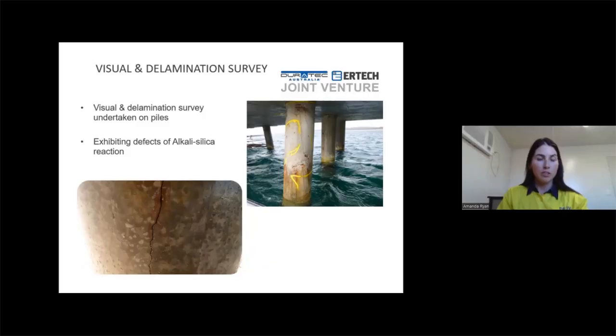A visual and delamination survey was undertaken on every pile. As you can see in the photo on the right, here is where the delamination occurred. Large areas of the concrete surface of the pile were delaminated, and here we found exhibit defects of alkali-silica reaction. You may ask, what is alkali-silica reaction? Well, it's most commonly known as, you've probably heard of, concrete cancer. It's the swelling reaction that occurs over time, which causes the concrete outside it to crack, therefore letting air and moisture in, deteriorating the reinforcement structure further.